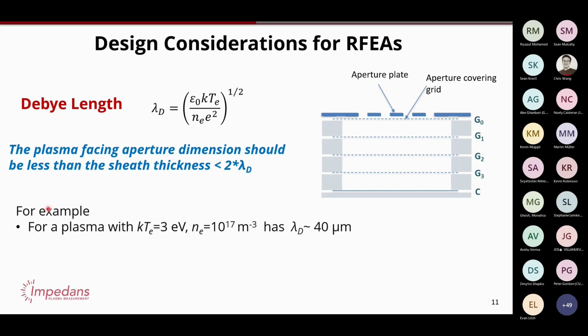Just an example calculation here for a 3 eV plasma, so that's the electron temperature, which is pretty typical. Plasmas are typically in the 2 to 7 eV range in terms of electron temperature. And a plasma density of 10 to the 17, where semiconductor plasmas are typically 10 to the 16 to 10 to the 18.